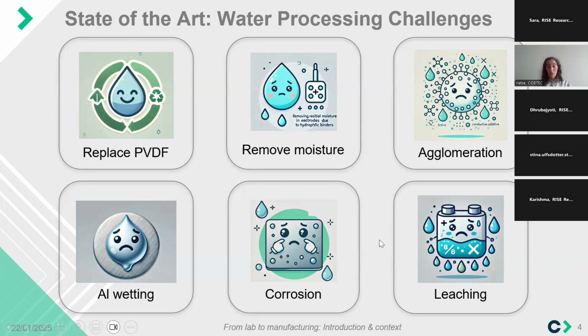Issues related with the high basicity, high pH of these suspensions, these slurries in water, is that it affects, corrodes and passivates the aluminum foil, the current collector on which we coat to manufacture these electrodes, and also affects the wettability of these water-based inks or slurries on this aluminum surface.